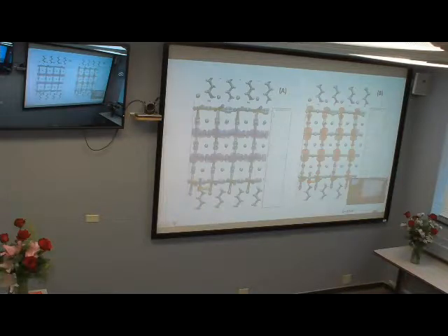But anyway, so here the surface is completely isolated by these ligands, right? And they do not contribute to your HOMO-LUMO gap, while the other ones have these orbitals of top and bottom completely occupied, and this probably caused this difference in the band gap, right? So the organic layer works as an insulator, and the inorganic does not. Yeah. Okay. Let's thank David once again.